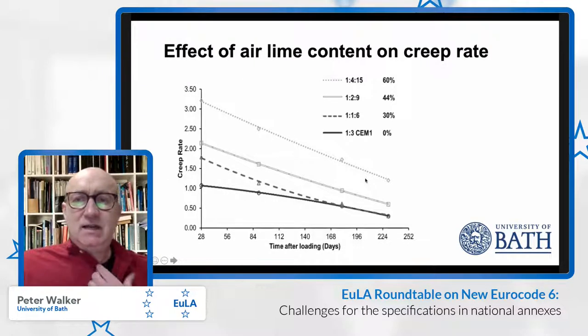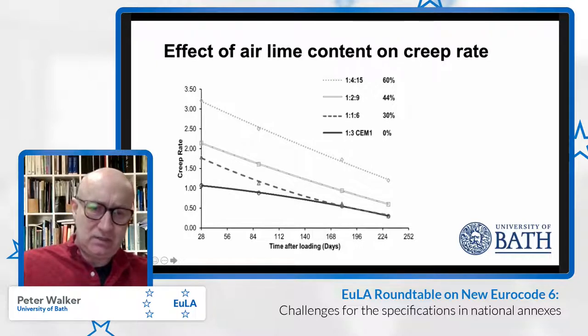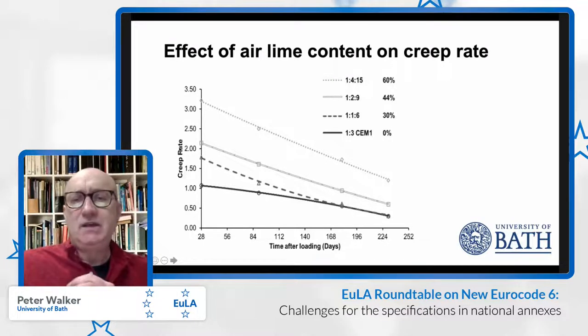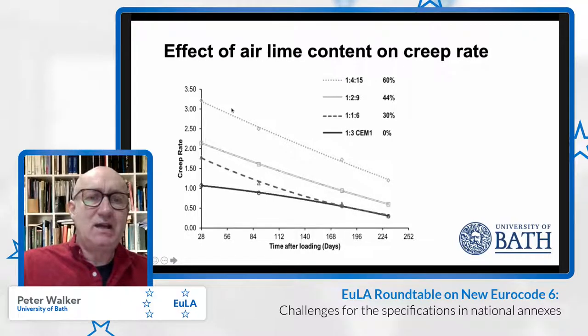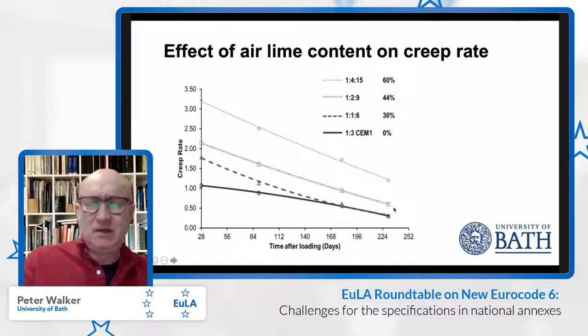Presented in a slightly different way, here we have the time since loading and the creep rate. The creep rate is the slope of the curve that you've previously seen. And we see that the slope, as recognized by the curved form, is decreasing. So the creep rate is decreasing with time, as you can see across there, presented here at four different time intervals.